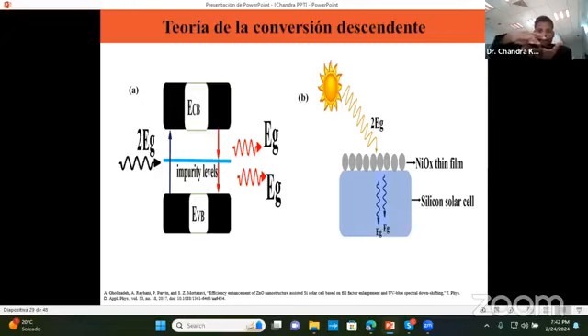Understand? The material requires only 1.2 electron volt energy, because that is the optimum band gap of a silicon cell. But the sunlight coming has high energy, like 2.4 or 2.5 electron volt, so that energy will never be absorbed by the material because it is larger than the optical band gap or electron affinity, which I will discuss later. So we will deposit, coat, or evaporate a layer over the silicon substrate that has the ability to convert this 2 EG equivalent photon into two different EG photons. The energy advantage is that this photon has band gap energy of 1.2 electron volt, and this one is also having energy 1.2 electron volt.